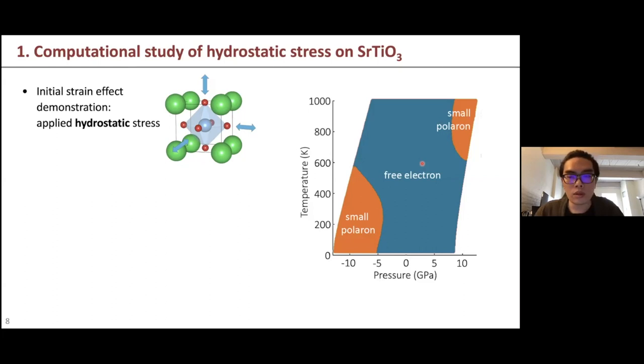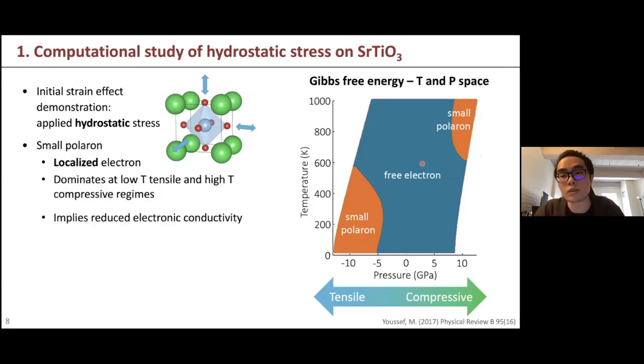So in strontium titanate, the electron can take two forms. One is just the free electron, as I show here, and the other one is the small polaron. The small polaron is basically just a localized electron on titanium. It can localize on different kinds of cations in different materials, but in strontium titanate it localizes on titanium. So we can just imagine that some titanium becomes 3+.